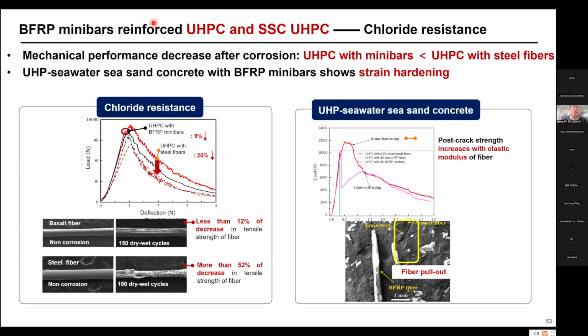Here it shows that for UHPC, we can also use these mini bars to produce it, and still under seawater corrosion. After some dry-wet cycles, you can see that for basalt fibers, the strength only loses 12%, but for steel fibers, after the same cycles, it loses half of its strength. That's in a very severe sea environment. So that shows the advantages of these mini bars.